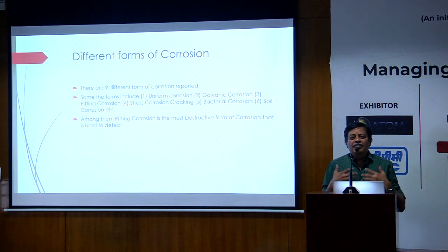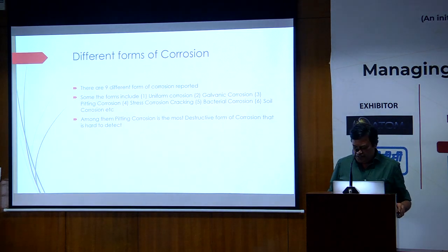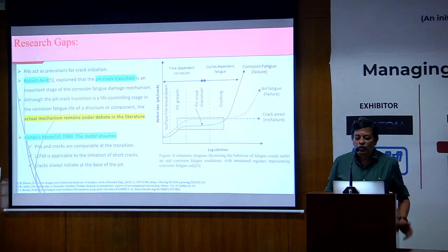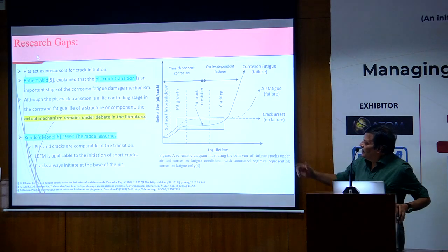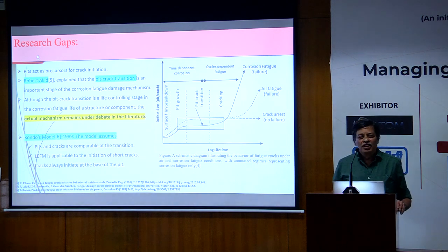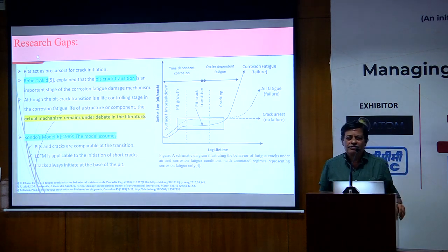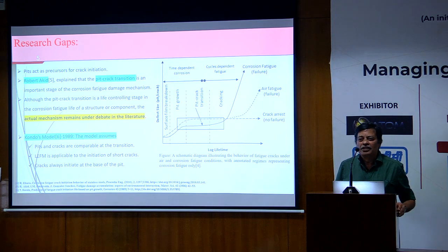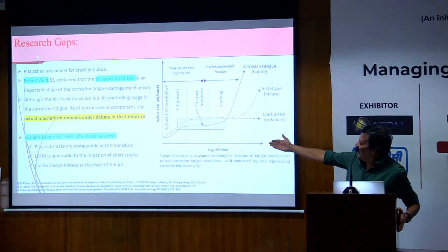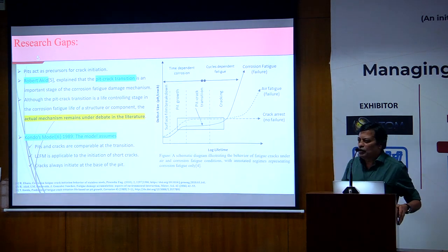So when we have physics-based models, then when we go to the larger prediction of trying to build the corrosion database, it's very essential to have this. So if you look here, how do the pits form? Most of the materials are coated. They have a surface coating film. But this film keeps on breaking, and after some time the breakage happens and the pit starts growing.